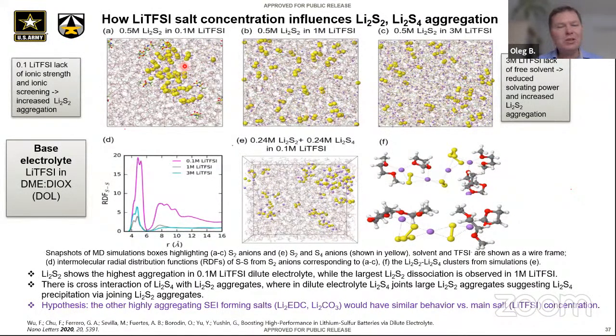And clearly at low concentration, you do have plenty of solvent, but it's even much more aggregated. And quantitatively, we can look at it here as this RDF for sulfur from Li2S2. 1 molar provides the lowest aggregation. At 3 molar, aggregation of sulfur increases, and 0.1 molar is the largest.